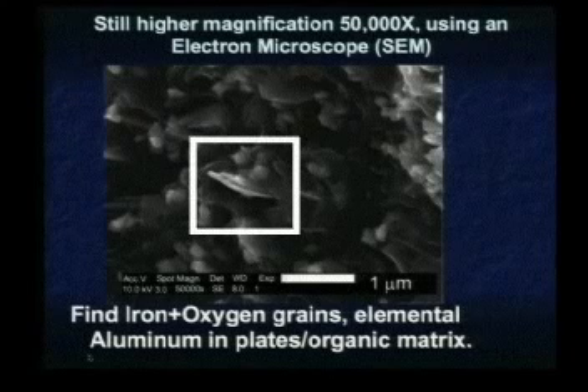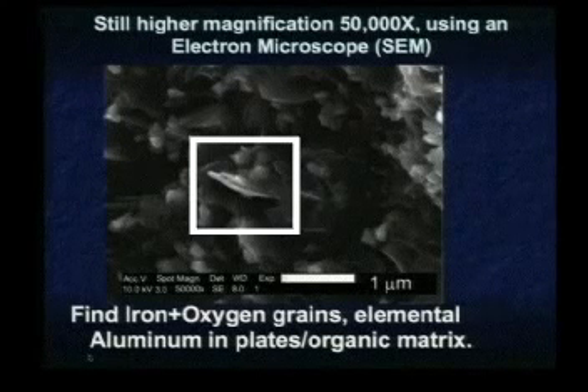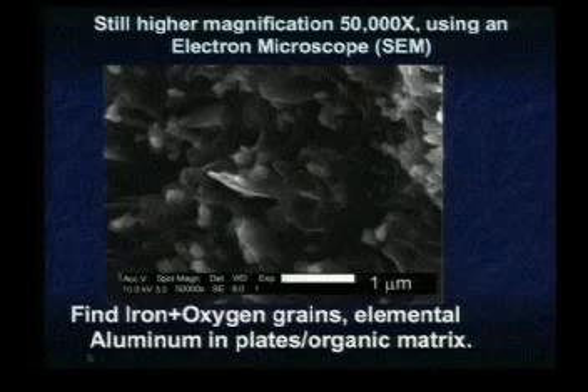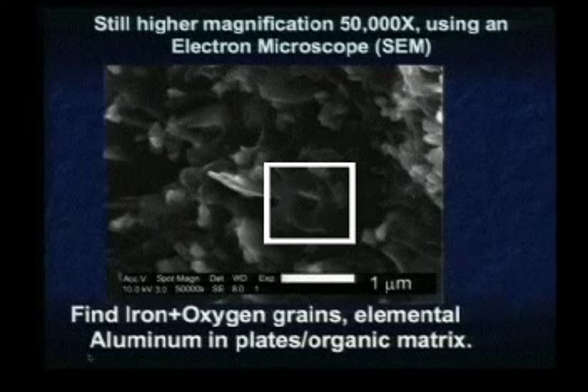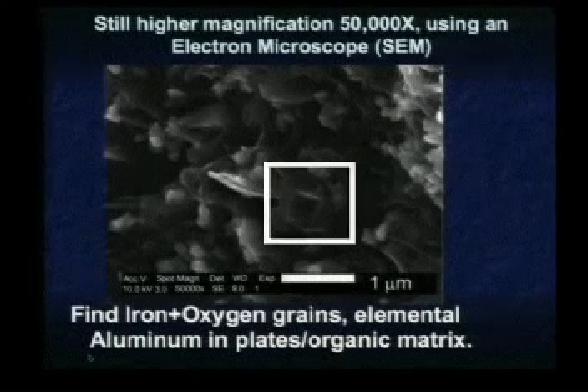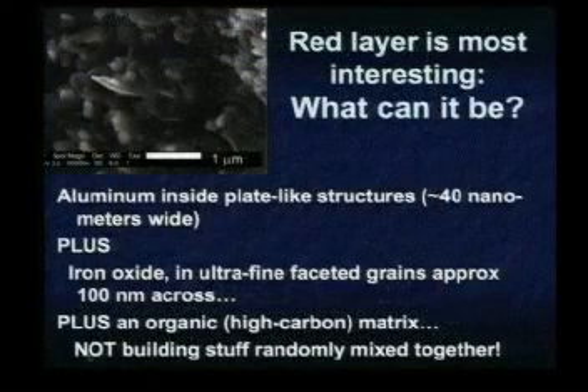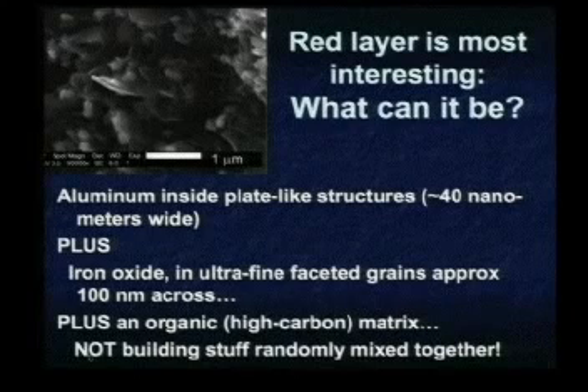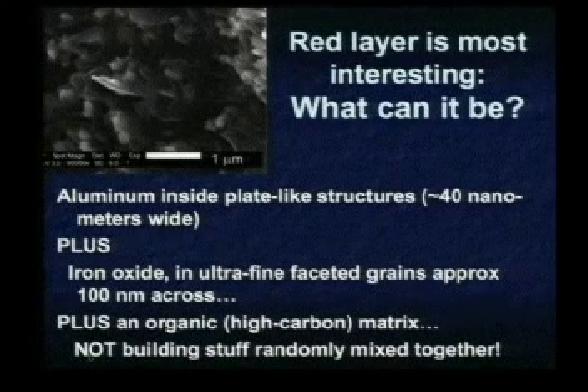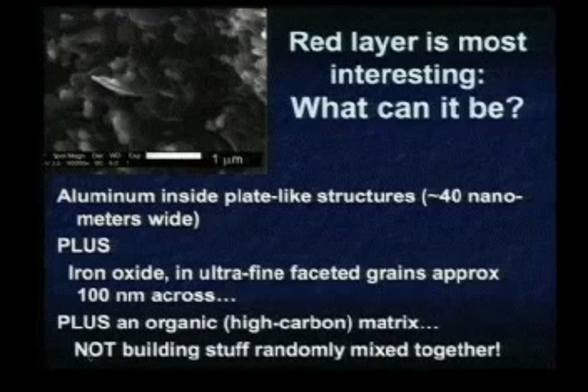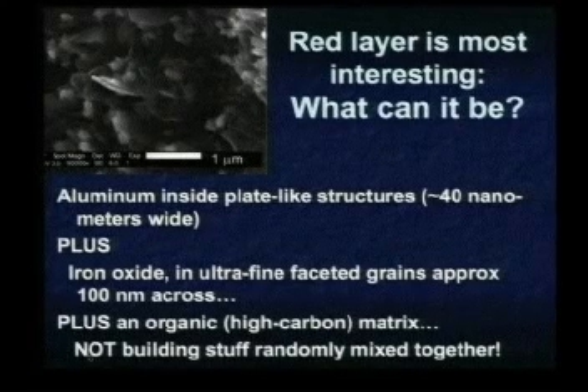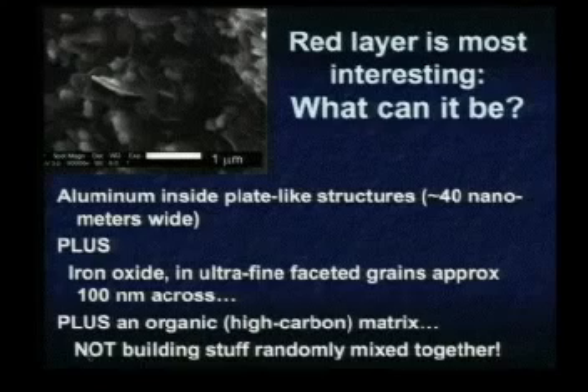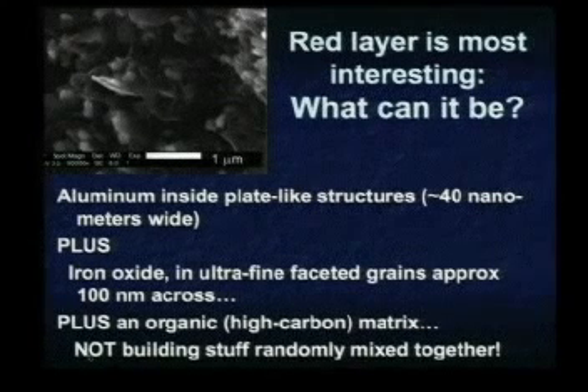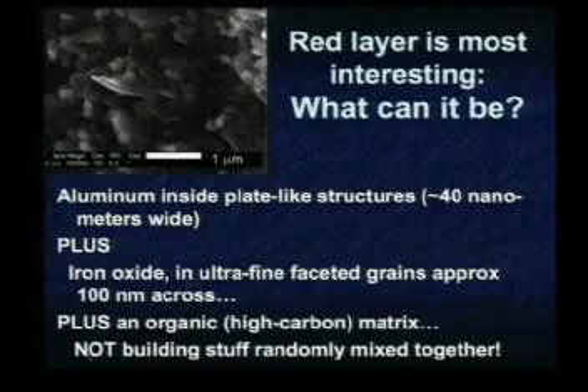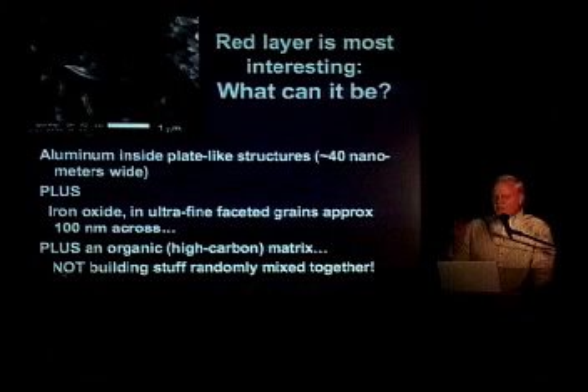And the aluminum is found in these plates. Can you see right near the center below that set of grains, there's aluminum. And then around this, there's this kind of wavy material. This is an organic matrix rich in carbon. Now, this red material is most interesting to us because it has aluminum inside these plate-like structures. The plate-like structures are quite uniform in thickness from what we can observe with the scanning electron microscope, 40 nanometers wide. Plus, the iron oxide appears in these ultrafine faceted grains, approximately 100 nanometers across, and again, very uniform.